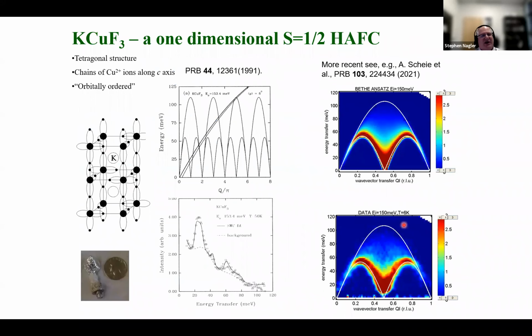in many different systems. I'm giving here as an example potassium copper trifluoride. Now, in fact, I would argue this is a quasi one-dimensional spin-1/2 Heisenberg antiferromagnet. And it's probably the first one, well, on 2 accounts. It was one of the first experiments that got something really useful using time-of-flight inelastic scattering on a single crystal that was anisotropic.